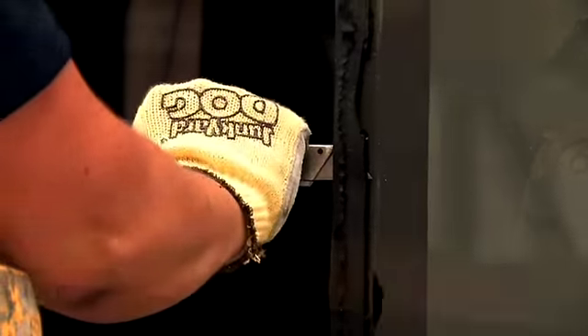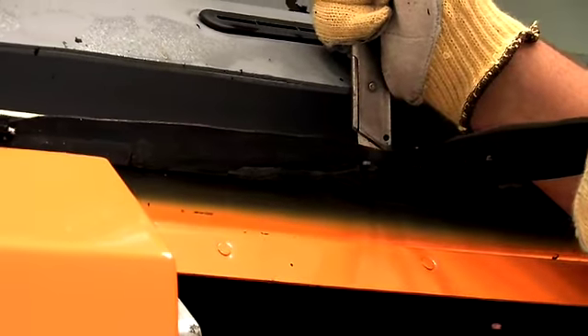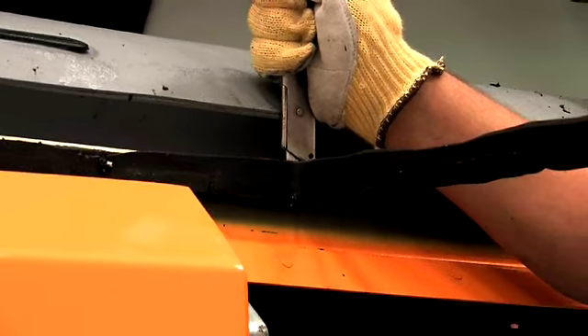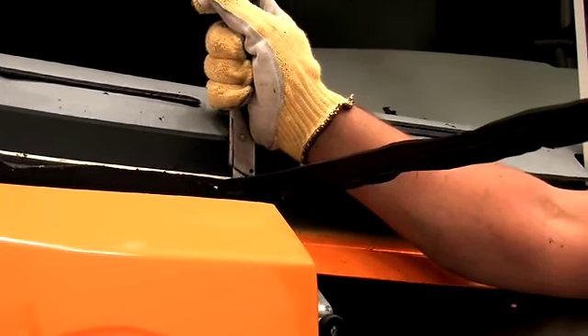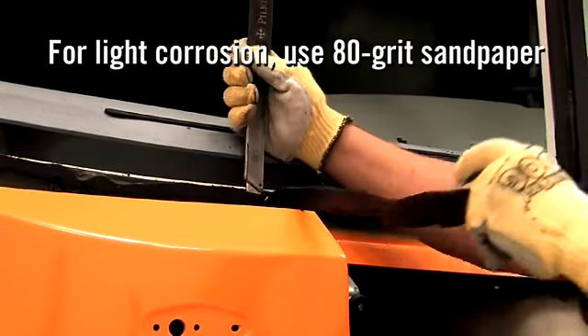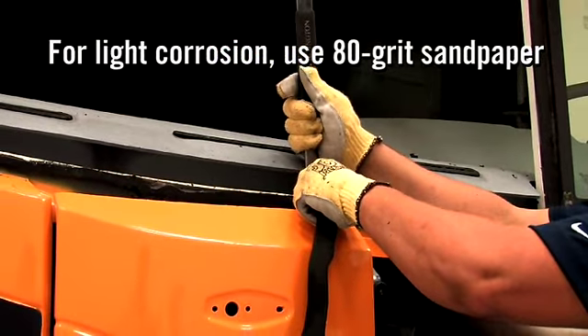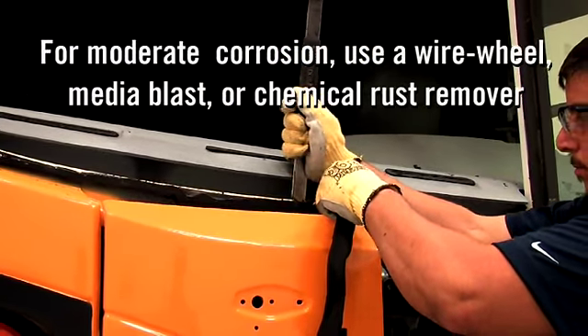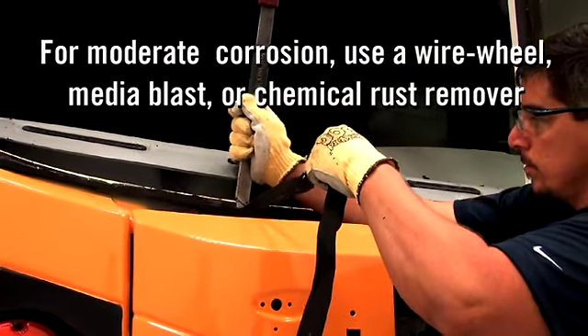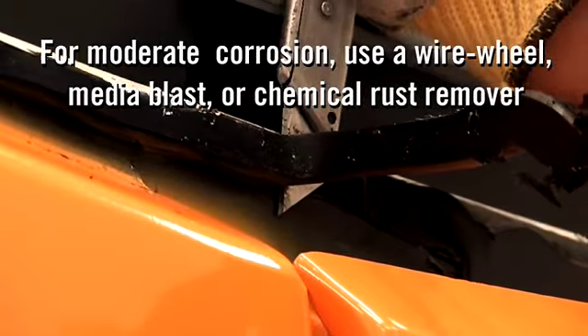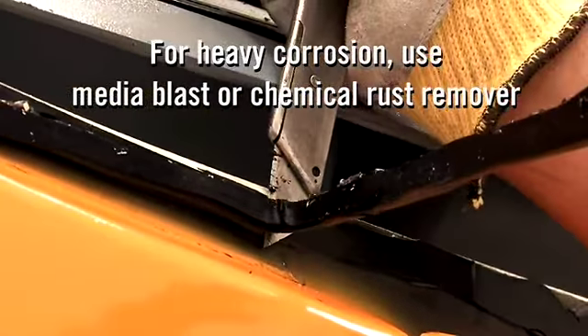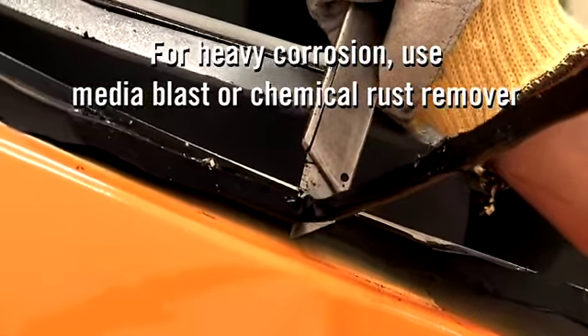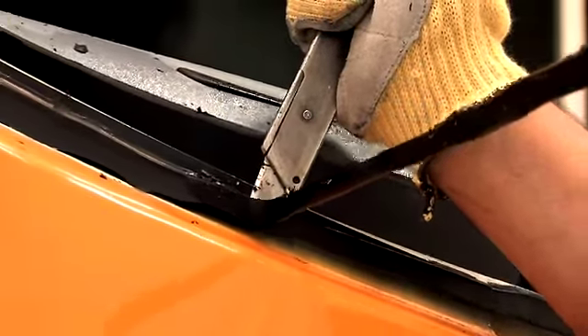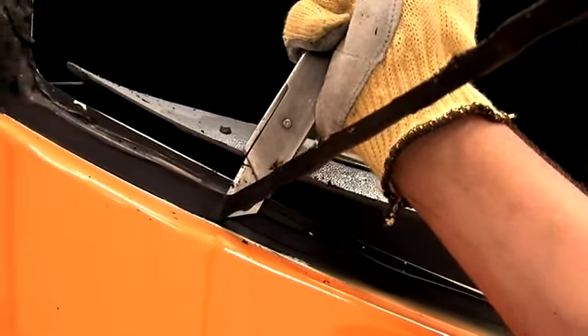Because the bus we're showing here is a new bus, we won't find any corrosion. But if we did find light discoloration of the metal, we'd clean it with 80-grit sandpaper. We'd clean moderate corrosion with a wire wheel, media blast, or chemical rust remover, and heavy corrosion with media blast or chemical rust remover. In an extreme case, perforation would require metal bodywork repair.